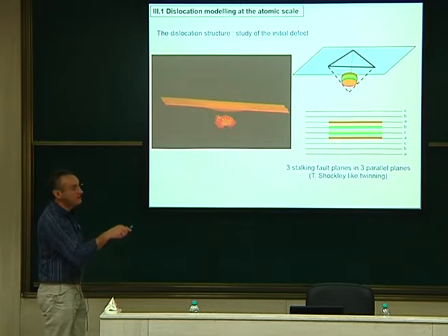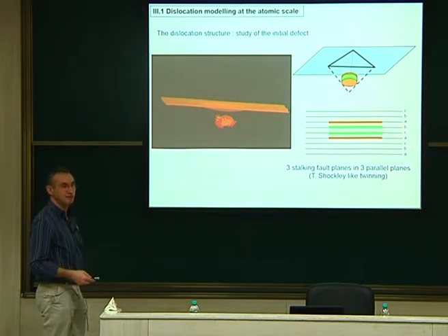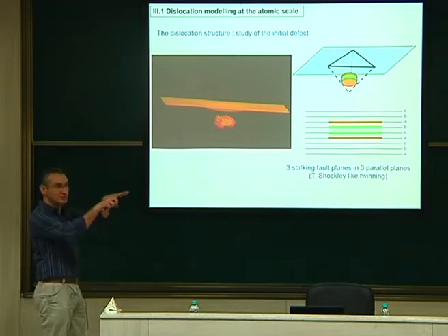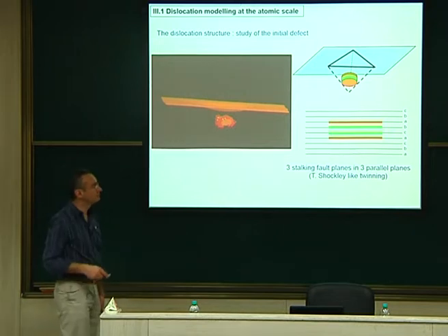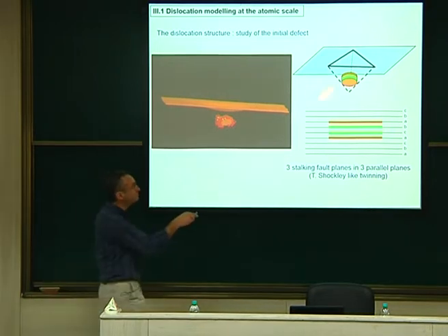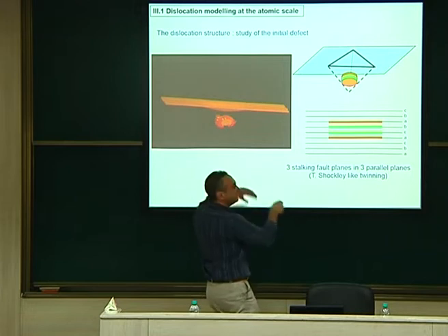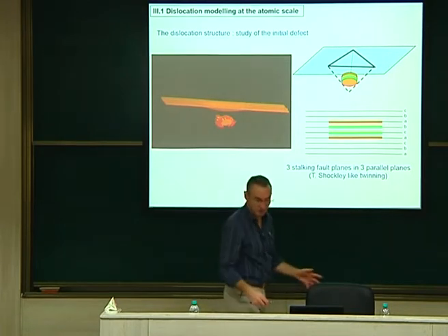So it's like a beginning of a twin, because you have CBA, you see ACB, and you have ACB here. So there is a mirror symmetry between the two sides. So this is a twinning, okay? You understand this twinning mechanism? Twinning is the mirror symmetry of your stacking. So this is what you have here. We clearly have a twin, a small twin. And quickly the twin decomposes and forms dislocations. Okay?